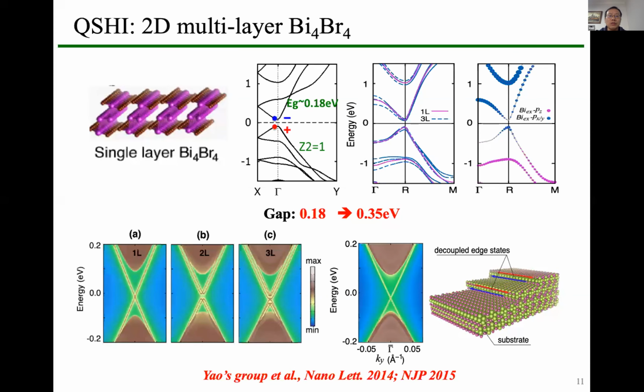Actually, if you continue to do these calculations, you will find that even-layer thick structures are trivial, but the odd-number thick layers are non-trivial. So the other very important thing is that because the interlayer coupling is very weak, these edges on the surface still survive the coupling between the interlayers. So this means that if we have a surface and find some very clean edge on the surface, these edges can host topological edge states. So this means that this kind of material is very promising for future devices or for future study of their topological properties.